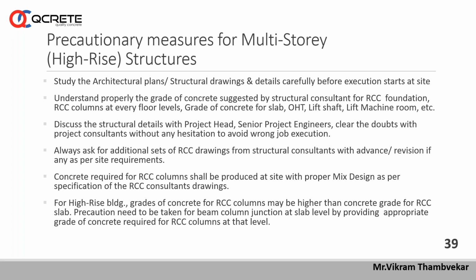One more thing is here: when your chemical admixture comes from the drum, every time it is necessary to stir it properly before using, manually or with the help of a pump if you have a batching plant. I have seen people simply operating the pump installed on the drum and they don't take care of stirring the chemical admixture. So what happens, the solid content gets settled and only the water content gets mixed with the fresh concrete. Because of that also you won't get proper workability as well as proper strength. So all this care shall be taken at the RMC plant as well as at the site itself.